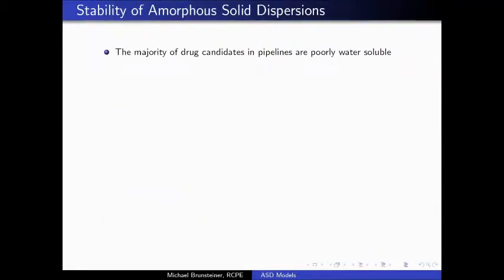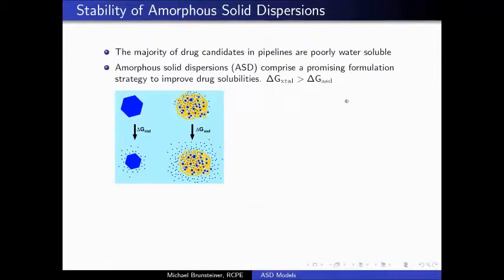So, one of the recurrent issues that's getting more and more prevalent these days is barely soluble drug candidates. Actually, one of the culprits for having all these barely soluble drugs is you guys who make all these drugs from virtual screening, which are typically poorly soluble. So one idea to cope with that is to make what they call amorphous dispersions. This is based on the fact that if you have an API molecule, a drug, in its crystalline form that's poorly soluble, then you can increase solubility by using the amorphous form or state of this API.